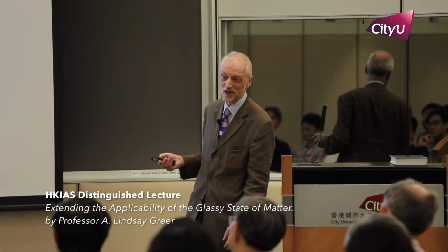But it also raises the question of, if we wanted to get even faster switching, well, we certainly shouldn't go in the metallic glass direction. They're, in fact, the glassy state is too good. It's too difficult to crystallize. What you should do is head in the pure metal direction, which brings us to the question of, can you get a pure metal glass? Well, it seems you can.